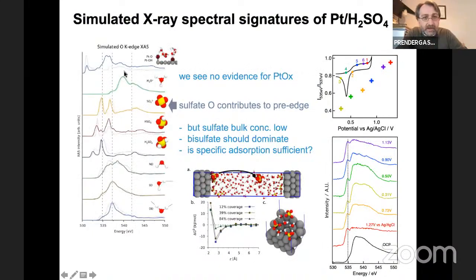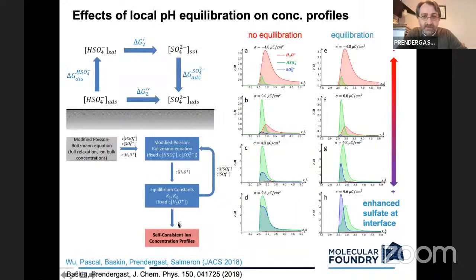So I had mentioned that the sulfate contribution seemed to be dominating the peaks that were observed in experiment and defining this potential dependence. And so what we did was we built one of these continuum models to describe the system, where we didn't just rely on details of specific adsorption because that wasn't sufficient. We also coupled together three species. So the bisulfate population, the sulfate population, and the one thing that connects the two of them, the hydronium population, or the protons in the solution, so the pH. And so the concept here is that as you approach the interface, if you have different populations of these species, you'll basically be creating a local pH that is different at the interface than it might be at the bulk.